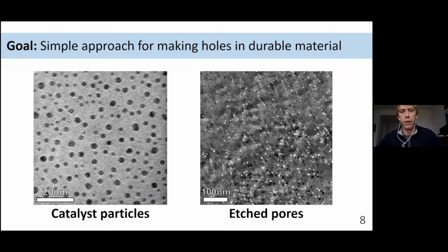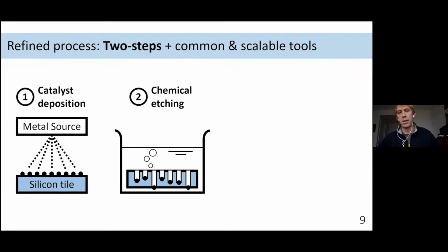So really the bulk of our innovation was around minimizing the complexity, minimizing the cost of this process. And eventually we were able to take it down to about 2 steps using only common and scalable tools that are available at scale in industry today. And so again, the first step is that catalyst deposition. We currently use a sputtering approach to deposit that metal on the silicon tile. And the second and final step is that chemical etching step.